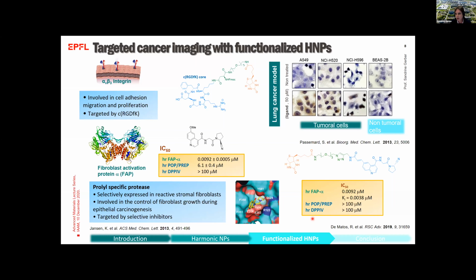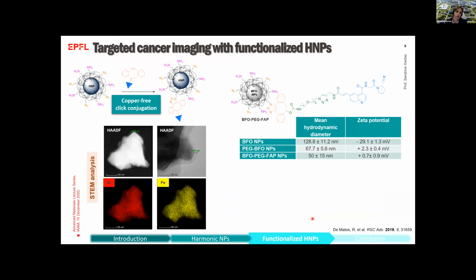Then comes the conjugation of those ligands at the surface of the nanoparticles. We based our protocol on the possibility to make a click reaction at the surface of the nanoparticle. This click reaction uses azido groups introduced on the coating polymer and an activated triple bond, represented here, introduced on the targeting ligand, to make a spontaneous 3+2 cycloaddition, giving rise to the covalent linkage of the nanoparticle to the targeting ligand without the need for any additional cross-linker or chemical reagent.